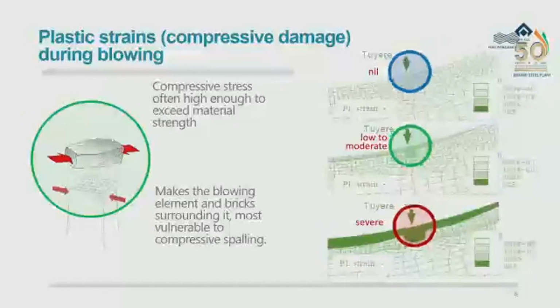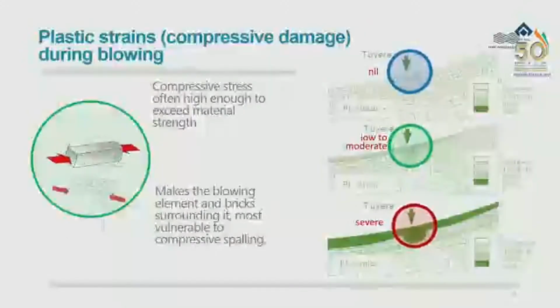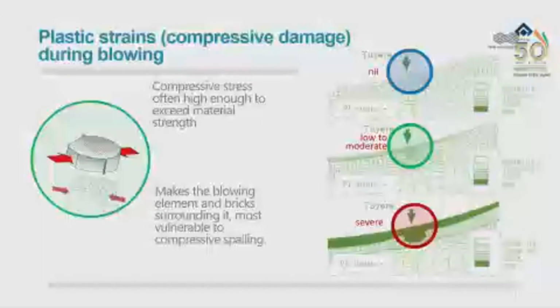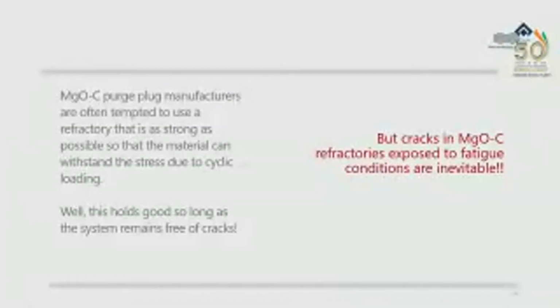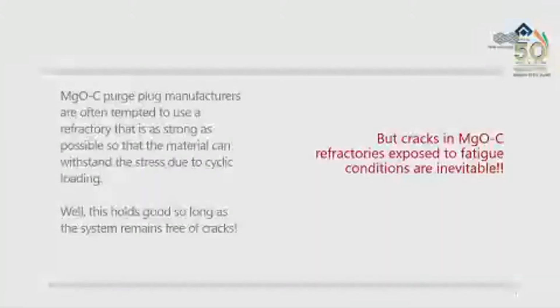It is often high enough to exceed the material strength. So it makes the blowing element and the brick surrounding it most vulnerable to compressive spalling. And these are the degrees of compressive spalling, the plastic strains from nil to low to moderate. So MgO-C purge plug manufacturers are often tempted to use a refractory that is as strong as possible, so that the cyclic loading and unloading I was referring to will be taken care of.